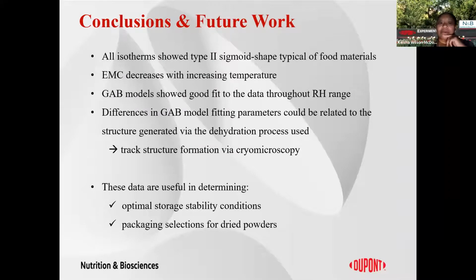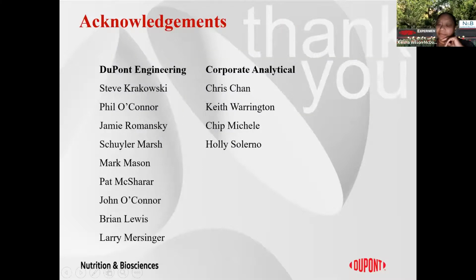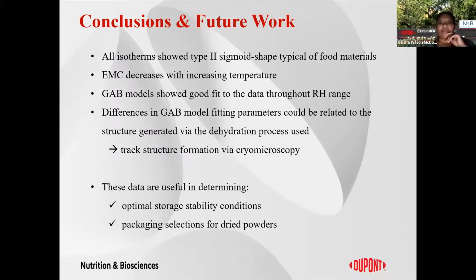So in conclusion, I want to just show that we did do some moisture absorption behaviors of our skim milk powders produced by both freeze drying and spray drying. And we saw that both of those showed type 2 sigmoid shape behaviors that are typical of food materials. We saw that the equilibrium moisture content decreased with temperature, as we see very often with food materials, and that the GAB model showed good fit through the full range of the humidity that we studied.